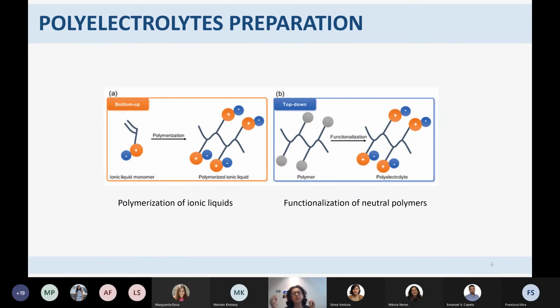So how do we prepare polyelectrolytes? Typically, we prepare polymer electrolytes in two ways. One is a bottom-up approach, where we pick an ionic liquid monomer and polymerize it, and we get a polymerized ionic liquid. There is also a top-down approach, which is functionalization. So I pick a neutral polymer and functionalize it in a way that I get charges. Typically, I do an alkylation of a group, and that's how I introduce the charges. It is very difficult to use the first approach, the bottom-up polymerization, to prepare polyionic liquid membranes, because typically they are of low molecular weight, and so they are not film-forming. I cannot make films with them. And so typically we go with the second approach.